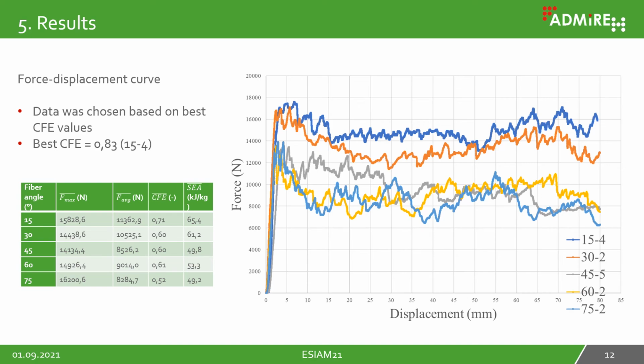The results of the quasi-static compression testing are shown in the diagram on the right. The diagram shows the force displacement curve of one specimen of each set. The data was chosen based on the best crush force efficiency value of each specimen set. The best specimen with a fiber angle of 15 degrees has a crush force efficiency value of 0.83.